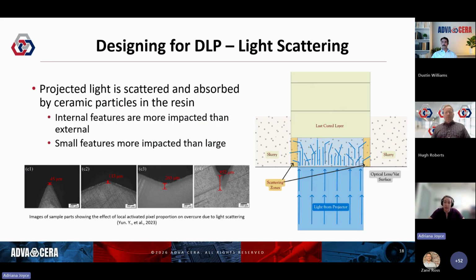The same pixels that are approximating the native shape are projecting light up into the slurry. Fortunately, the light follows the laws of physics and doesn't stay contained in a perfect little square column, convenient as that would be. As the light travels up into the slurry from either direction, above or below, whichever way the projector is going, it encounters the ceramic particles that are suspended in the photopolymer resin. Those particles absorb and scatter the light, and the scattered light encounters photoinitiators outside of that desired curing zone. This causes overpolymerization and increases the dimension of our part outside of the design value.